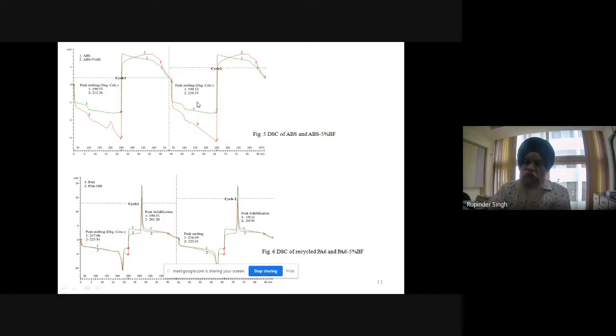And once we observe that in the second cycle also, this was almost similar. So 190.55, 190.12. From the typical thermal engineering application, we consider this material as quite stable. So with the addition of the banana fiber, the thermal stability was not compromised, right? And in the repetitive cycle, I am getting a similar type of results. And secondly, the peak melting temperature is increased, so I can use that substrate for relatively higher temperature.